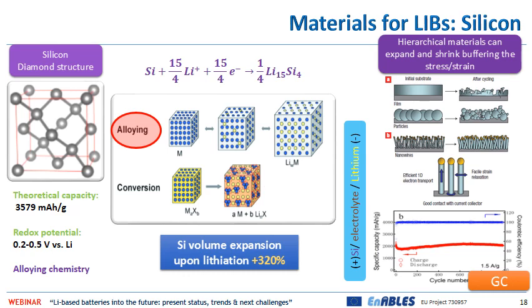Moreover, a very large volume expansion occurs during the alloying. In order to preserve the structure of the material, because obviously the lattice is completely destroyed during alloying, we need to play with morphology. In fact, it has been demonstrated in the literature that a 1D morphology can handle this big volume expansion, and the use of pillars or wires electrodes leads to possible reversible capacity that exceeds 2000 mAh per gram, as shown in the bottom panel on the right side, with a Coulombic efficiency that approaches 100%. The Coulombic efficiency is the ratio between the charge and discharge capacity, and so if we don't have any irreversible capacity, the Coulombic efficiency reaches 100%.